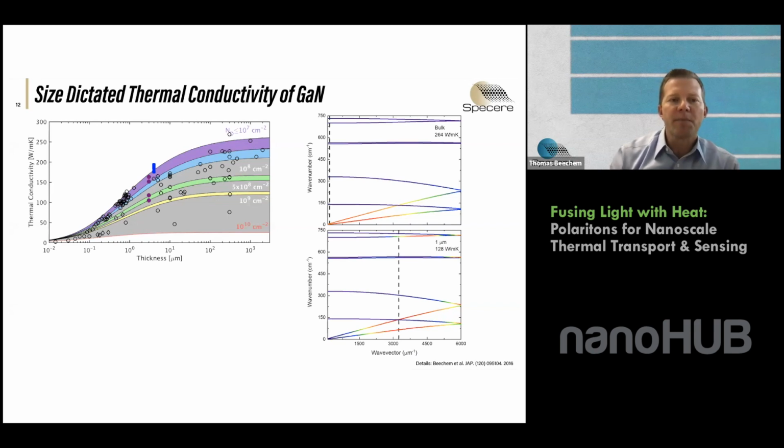That's what all those black dots are, and the things that I showed earlier are these filled ones. You see that, in general, very rarely do we get materials that have a thermal conductivity close to this textbook value of like 237 watts per meter K. And also in general, as your thickness goes up, your thermal conductivity goes up.